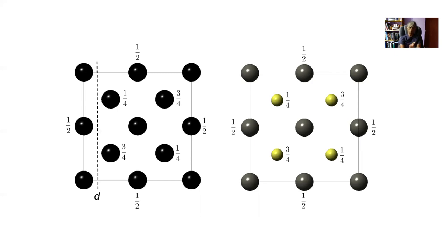In a point group where we are looking, for example, at macroscopic symmetry, you would not see such small translations, and therefore the glide plane would appear like a mirror plane. Now, there is no glide plane here because these two atoms are different. They're not identical species, okay?